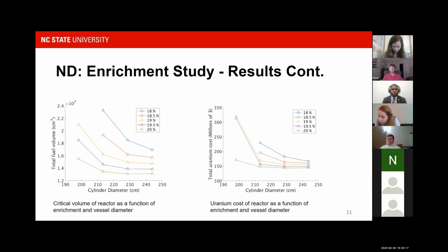We also calculated the total fuel volume, including the MSRE piping volume, and the total cost of our fuel. And the total cost of our fuel determined the enrichment that we used. We see that as we increased enrichment, we decreased the cost of the uranium needed for our reactor. However, there was a limit at 20% due to the legal definition of HALEU fuel, high-assay low-enriched uranium. Above 20%, we would enter into highly enriched uranium by that definition, and that would add additional legal and regulatory hurdles we would have to go through. That would overall increase the cost of our design. So we chose 19.5 atom percent because it minimized that cost, and it gave us adequate margin to increase enrichment later on if need be, in case our calculations were off.